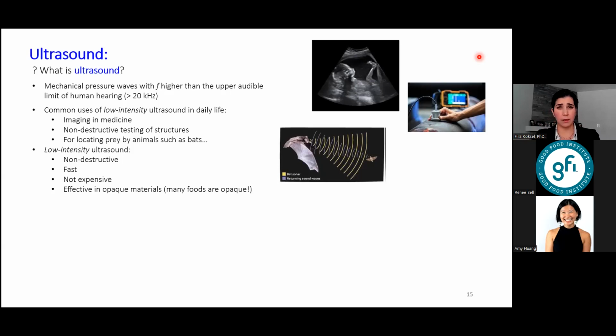Here, I'd like to take a second to emphasize that the ultrasonics that we use are low intensity, so they're non-destructive. So they're not supposed to cause any changes in the structure or the composition of the material being tested. Imagine it like this. If you're pregnant and getting an ultrasound image of the baby, that ultrasound has no effect on the baby, right? Or when you're testing pipelines, you just test the cracks and you're not really changing what's flowing inside that pipe. So it's the same idea.